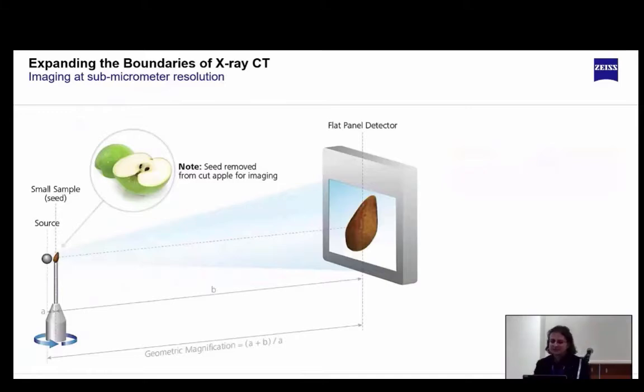If you want to do that with the traditional micro-CT using only geometrical magnification, you won't be able to do this. You will have to cut the apple open to get the highest resolution of the seed, and then extract the seed and put it as close as you could to the source. And yes, you get maybe a high resolution image, but it still will be limited to something in the order of 2-5 microns, depending on the type of system or the best conditions that you can get.